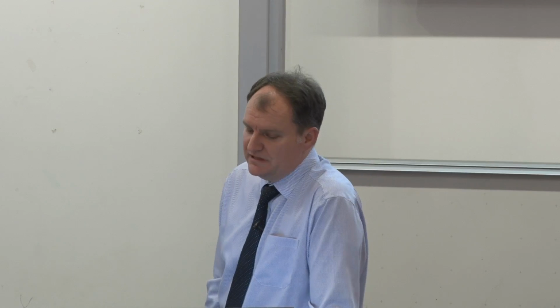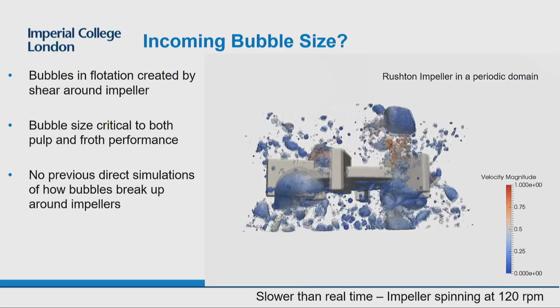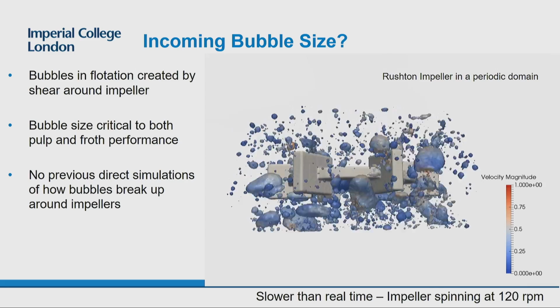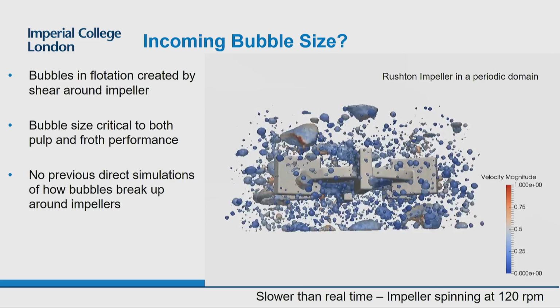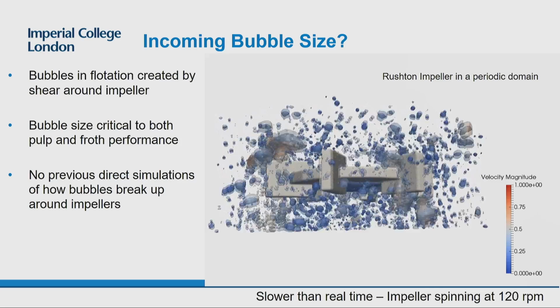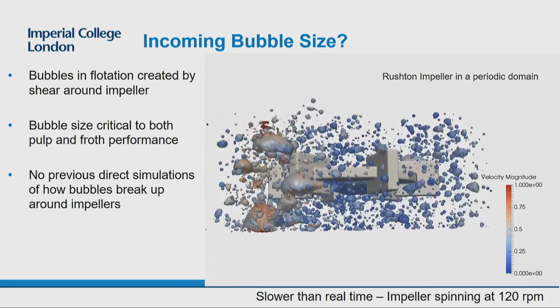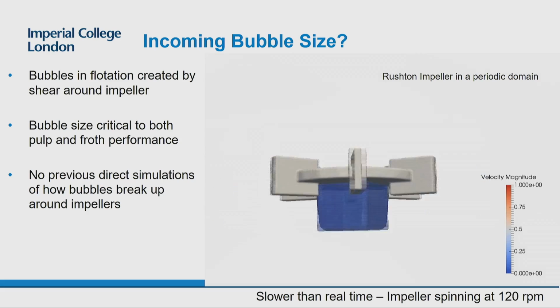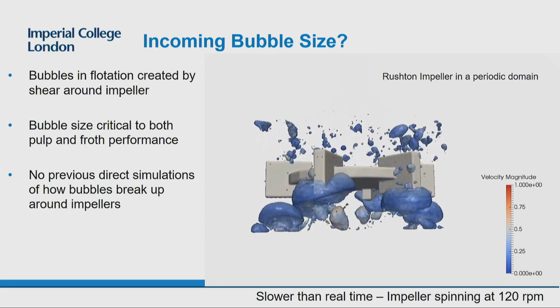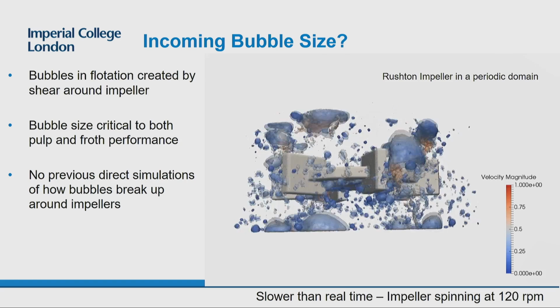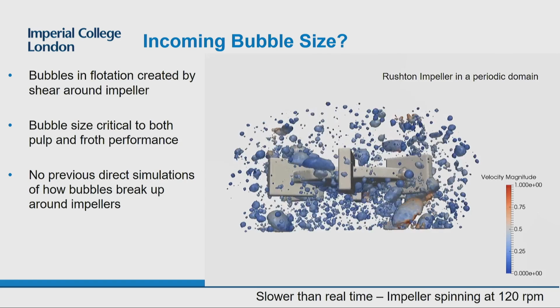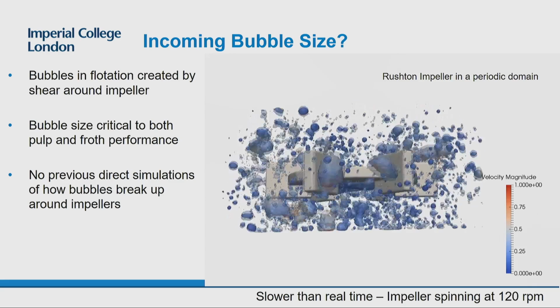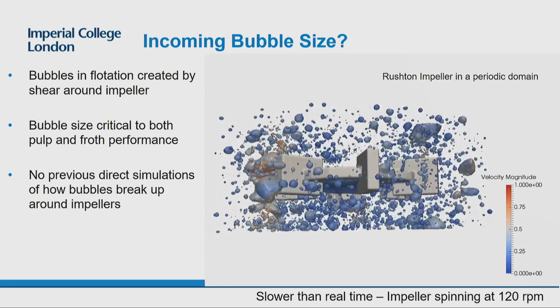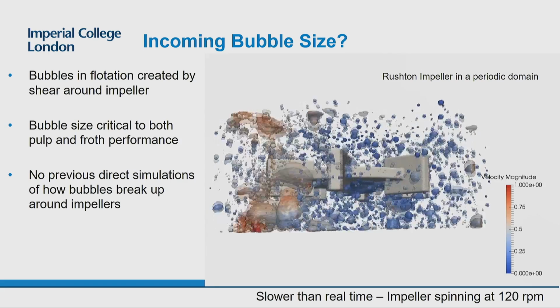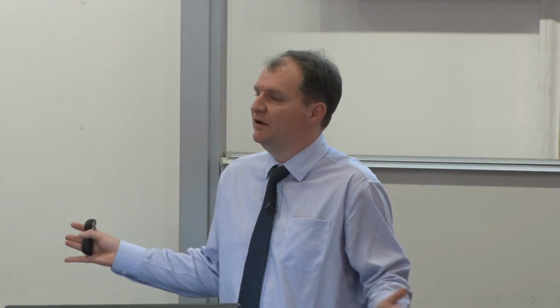I won't go into the details of that. The other important parameter here is what's coming into your froth, and the bubble size is particularly important. So we've started doing some simulations of bubble production. In a flotation cell, bubbles are actually produced by shear. They're produced by the spinning of these impellers inducing shear and causing the bubbles to be broken up. So you need to actually run simulations at the scale of the individual bubbles, which hadn't been done before. And the simulation code that I wrote to do this was based on a method called smooth particle hydrodynamics. So this is a meshless way of solving these equations.